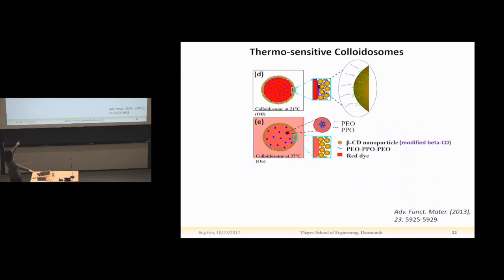So besides the particle-formed membrane, and besides the active materials encapsulated in the core, we also have a temperature-sensitive block copolymer encapsulated in the core. And this block copolymer will exist as individual molecules at room temperature. And also, they like to attach onto the surface of those nanoparticles. So this closes the pores in between these particles and switches off the release.